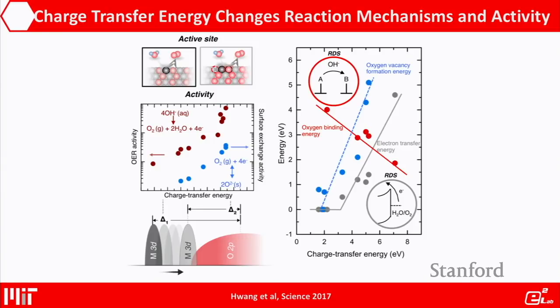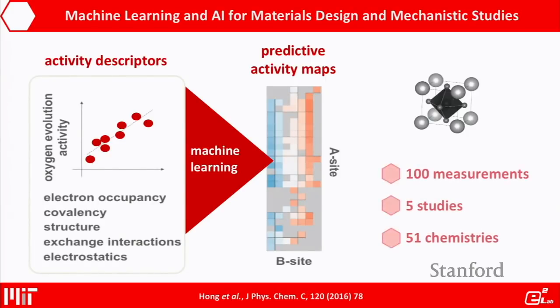So this gave us a clue. If we want to further increase the catalytic activity, we need to develop the surface so that it can dehydrogenate and deprotonate more effectively. There are certain cations that may have higher or lower pKa's, where we can modify the surface so that it promotes the deprotonation process and increases the oxygen evolution catalytic activity further.